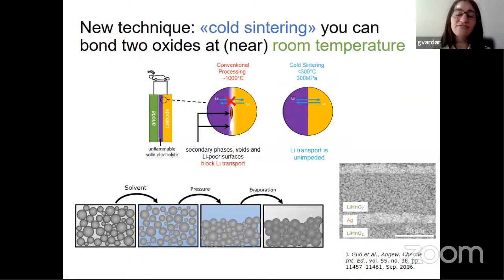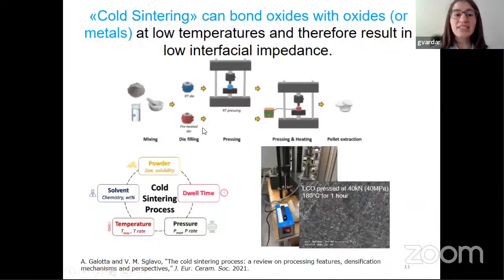The difference is that we would use a solvent and pressure in order to fuse these materials together. This is a technique that was highlighted in 2016 by Clive Randall at Penn State. And we're trying to apply this cold sintering mechanism to solid state batteries. And here you can see that you have solidified and made very nice interfaces between, in this case, silver and lithium manganese oxide by cold sintering. And you can see the interface is very sharp and non-degraded.